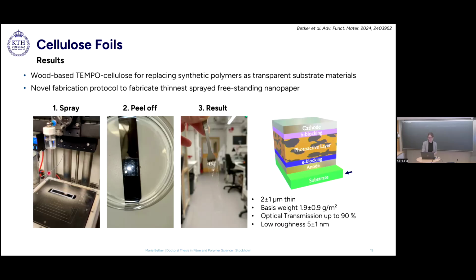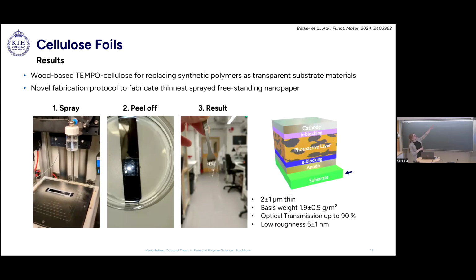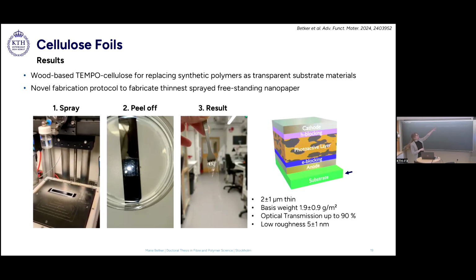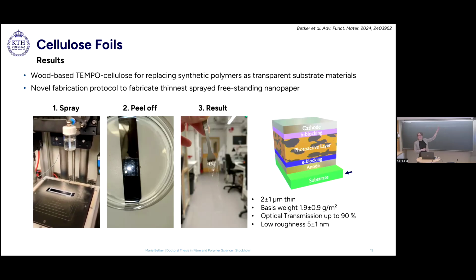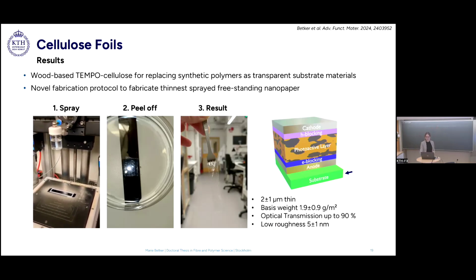In this first video, you can see the cellulose solution in water is sprayed directly, layer by layer, on a hot silicon substrate. Then I simply took this wafer and put it into a water bath, and you can see that you can simply peel off this foil. So this is only TEMPO cellulose, nothing else in it.